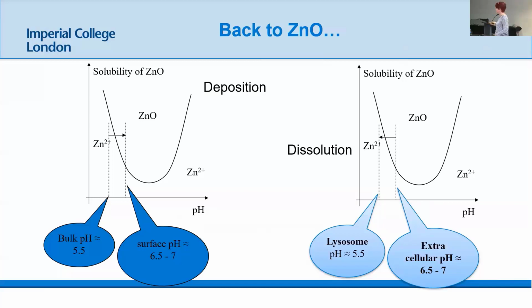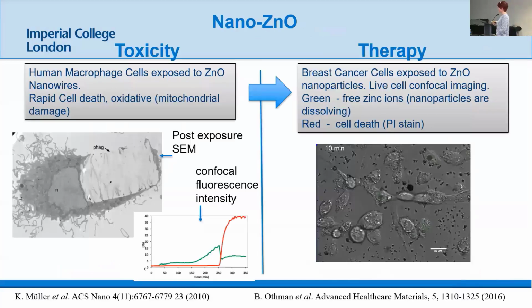So your extracellular pH is kind of neutral. In your blood plasma, for example, it's about 6 to 7. Inside a cell, inside a lysosome, it's around about 5. And that drops you over this barrier. So that means two things. It means zinc, which is an essential element, is not really very toxic for humans, but if you get enough of it locally, it's damaging.